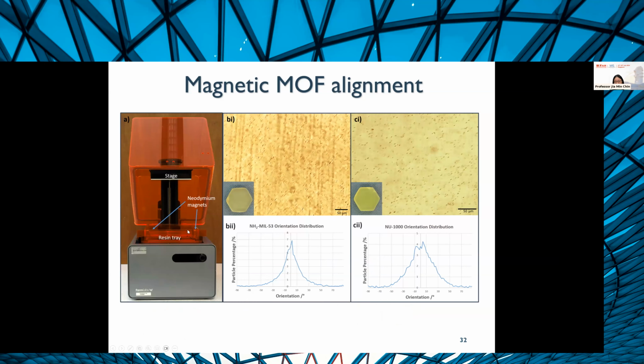One can integrate this quite easily into 3D printing simply by incorporating neodymium magnets and then printing it. You can get, of course, much more complex architectures than these hexagonal materials, but these are just a couple of examples, and you can plot the orientational distribution, and you can see that there is a clear preferred orientation.